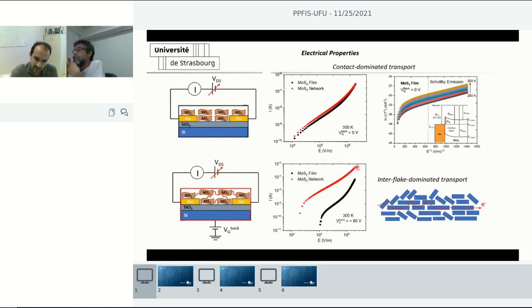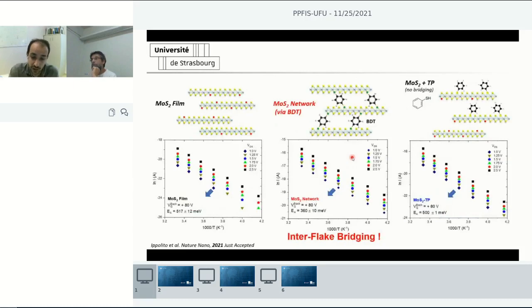And then what we observe is that the networks present higher currents than films by applying a significantly high backgate voltage. Meaning that now we are probing the interflake transport, and networks have an improved transport. Meaning that our hypothesis of using these molecules, the delocalized molecules, to improve the interflake transport holds: these molecules indeed improve the transport.